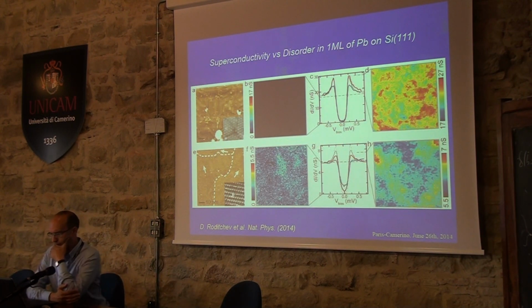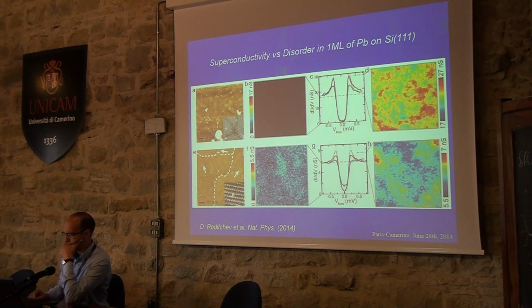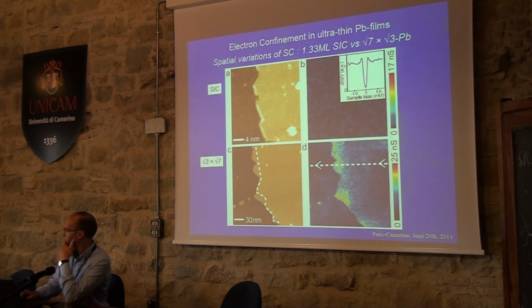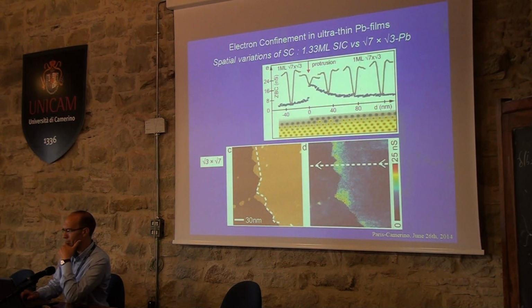In square root 7 by square root 3, when it is desorbed, you have a much larger variation of the superconducting gap, and specifically at zero bias. Take a look at the bottom series of spectra. You see that you also have variations of the quasi-particle peaks, but moreover, you have the beginning of gap filling, and this gap filling is completely unexpected for an S-wave superconductor. And so in this paper that I cited, the recent paper we published with Boris Altshuler and Lev Ioffe in Nature Physics in 2014, just one month ago, we give the beginning of an explanation of this unusual behavior. Next slide.